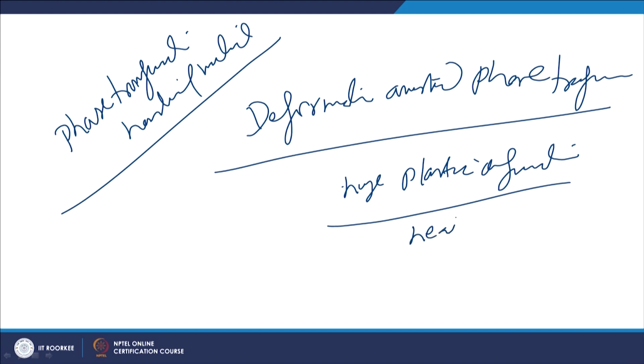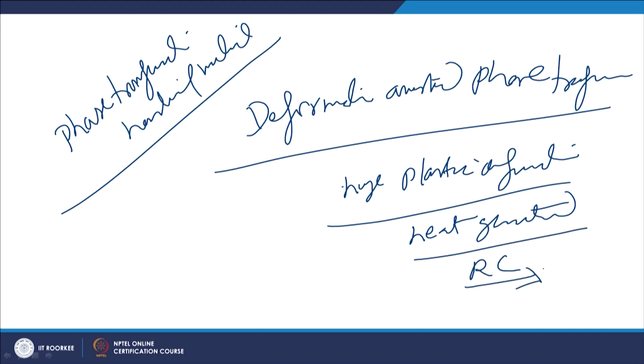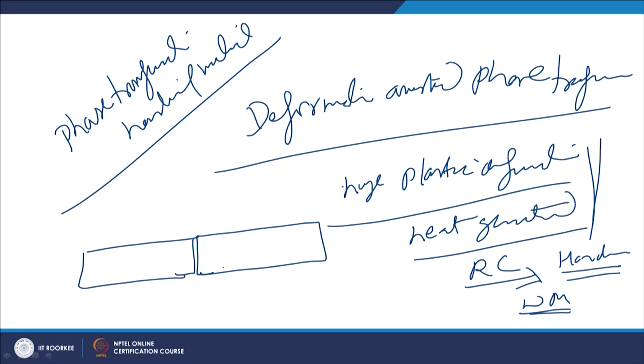In this process a lot of heat is generated, and the heat generated followed by rapid cooling again leads to the formation of hard phases in the weld zone as well as in the heat affected zone, but mostly this kind of phase transformation is experienced in the weld metal region. For example, when steel is welded through a plastic deformation based process, the huge plastic deformation of the faying surfaces leads to the formation of mostly martensite, followed by bainite and fine pearlite. While the base metal may have simply ferrite and pearlite, the controlled plastic deformation and the associated weld thermal cycle lead to the development of martensite, bainite and fine pearlite.